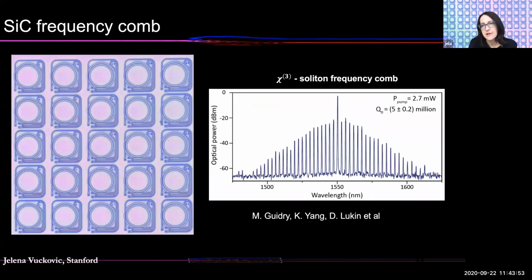And even more recently, this has not been published yet, we've demonstrated chi3 soliton frequency comb in silicon carbide, again with small threshold powers. This appears at the pump powers of 2.7 milliwatts, and this power is measured in the waveguide that is coupled to resonator. So this is actual coupled power to the waveguide. And again, soliton frequency combs are important because that's the regime in which you have a stable frequency comb on chip. They have not really been demonstrated in many materials, but this is quite exciting and actually comparable, for example, to Tantala platform that the group of Scott Papp at NIST is using to make practical microcombs.